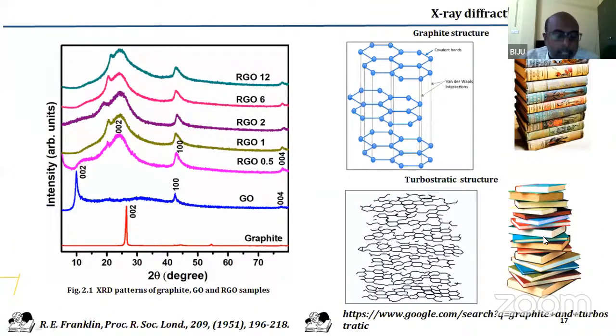Now this slide shows the XRD pattern of the graphite sample, graphite oxide sample, and the reduced graphite oxide samples for different time intervals. You can see that for graphite oxide, due to the intercalation of oxygen functionalities, the 002 peak of graphite has shifted to lower 2 theta angles, which means higher d values. And when you reduce, the peak comes back to almost the original position of graphite. But you can note that the peak has broadened much.